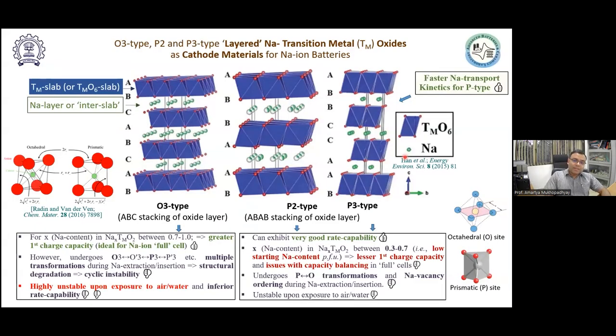Now, coming to the types of layered transition metal oxide, the structure types and the challenges associated with the different structure types. In a nutshell, because of the size of the sodium ions as compared to the lithium ions, sodium ions can take up two types of coordination, unlike the lithium ions. Lithium ion, when surrounded by oxygen ions, can take up an octahedral coordination. It can also take up a tetrahedral coordination, but more predominantly for the layered lithium transition metal oxide, the lithium ion stays in an octahedral coordination. Whereas sodium ion, which is a little bit bigger than the lithium ion, can take up an octahedral coordination and can also take up a larger prismatic coordination.